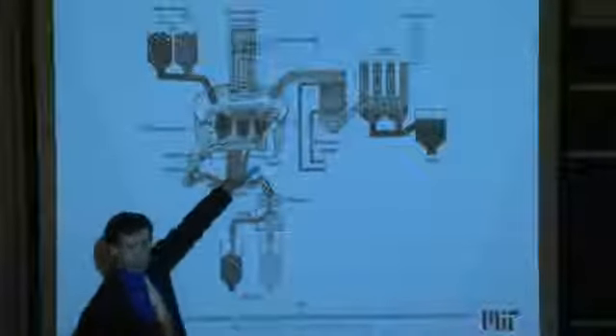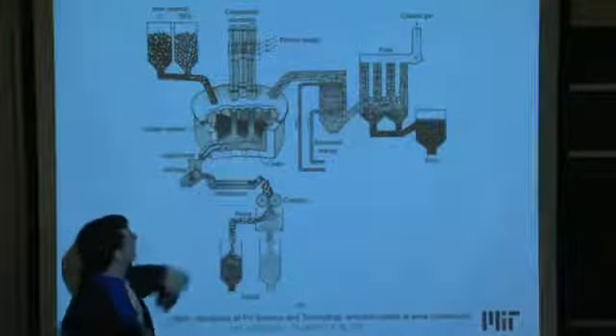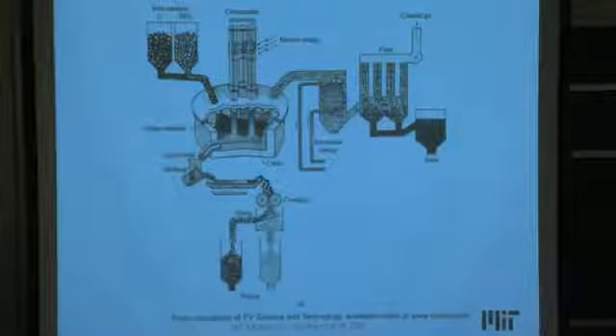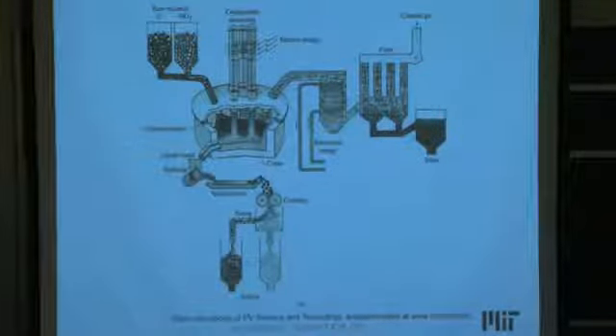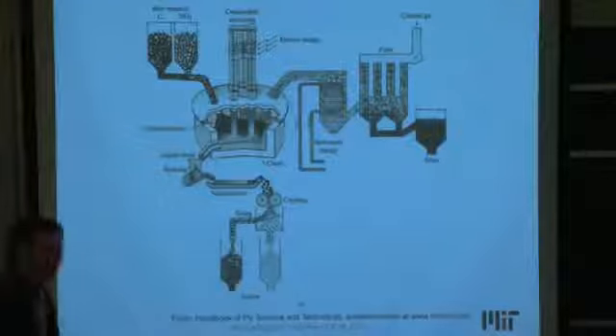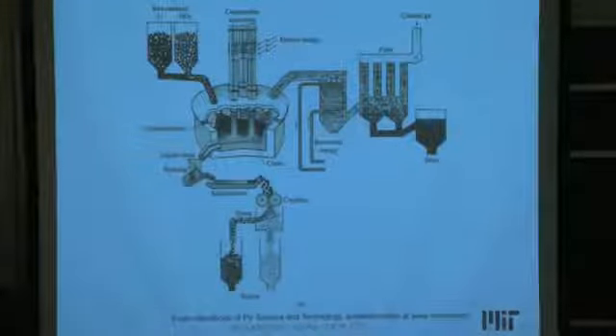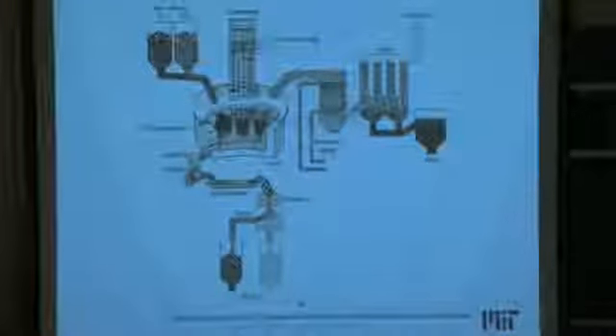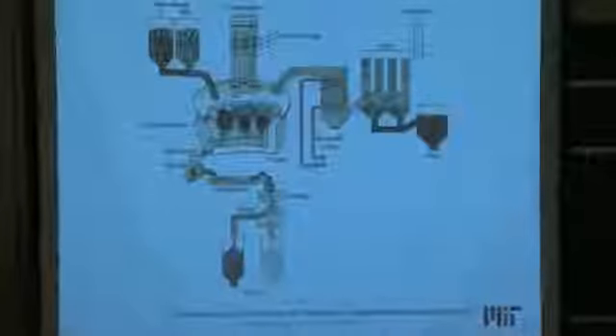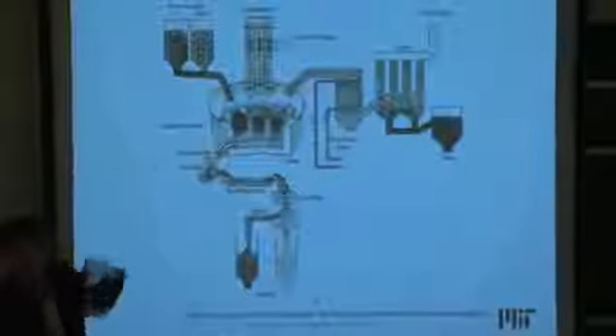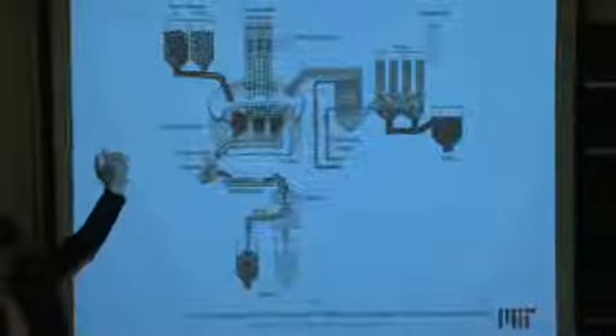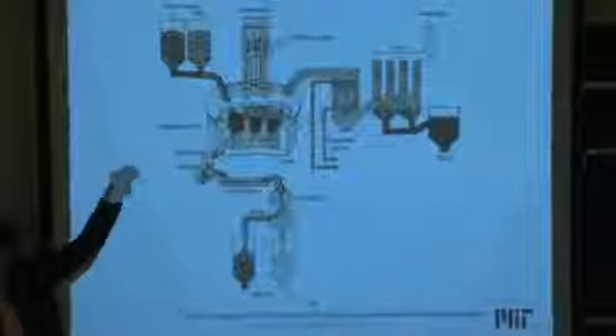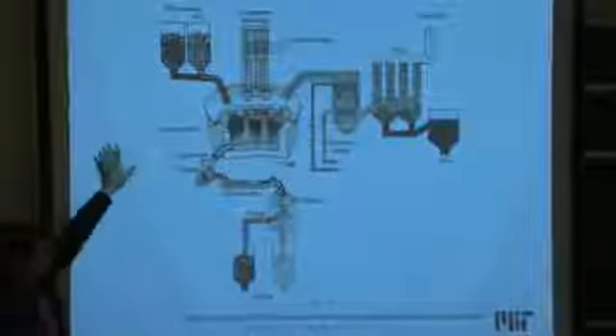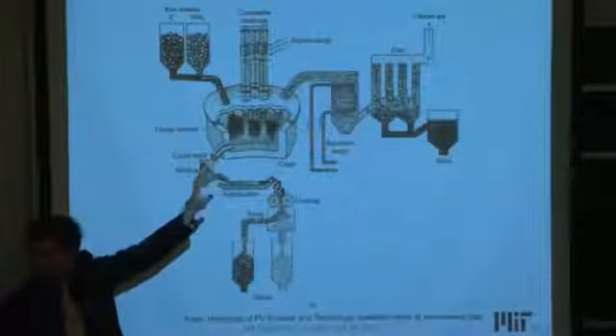also called a carbothermic reduction furnace. Very busy place, lots going on, extremely inhomogeneous if you were to take a cross-section, also in terms of temperature and in terms of the chemical states of the different constituent species. But the general reaction that happens is the carbon would much rather bond to the oxygen than silicon. And so the carbon steals the oxygen from the silicon and reduces the silicon to silicon metal. And CO2 is released. We'll get to that in a second.